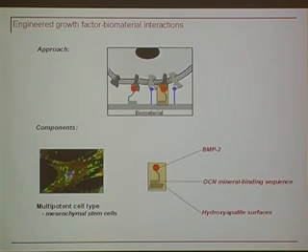So the first embodiment of this is a molecule that contains a peptide derived from BMP2, or bone morphogenetic protein 2. This is a molecule that can promote stem cell differentiation down the bone lineage. There's an osteocalcin-inspired mineral binding sequence that can bind to hydroxyapatite with strong affinity that can be potentially varied. And then there are hydroxyapatite surfaces. Hydroxyapatite makes up about 75% by weight of native bone tissue, and also is ubiquitous throughout orthopedics. So it's a good base material for us to start with because it's so common.